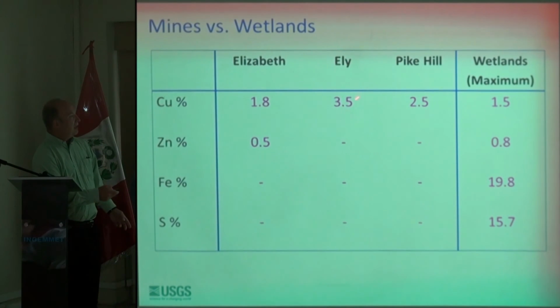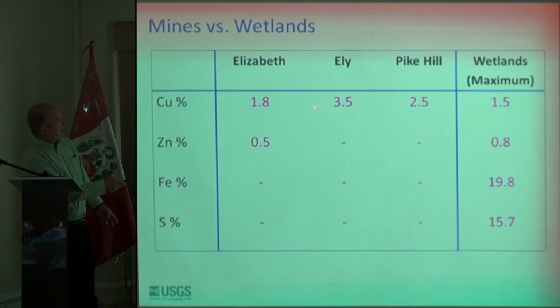Now what's interesting about this is that when you look at the ore grades that were mined at the Elizabeth mine, the Ely mine, and the Pike Hill mine, you see copper grades of around 1.8 weight%, zinc around 0.5, copper 3.5, 2.5 at these different mines.